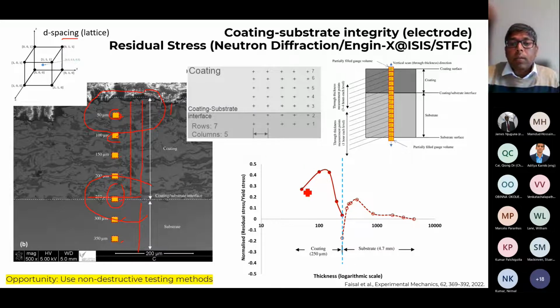So this is how the profile looks. You can see the strain is largely tensile. And it goes near to zero at the interface, but at the interface for the substrate there is very high compressive stress, and then it goes tensile. So that is how the coating-substrate system looks strain-wise. Now, we did many other investigations on this. The idea is we need to know how the strain value looks so that you can use it for further application.